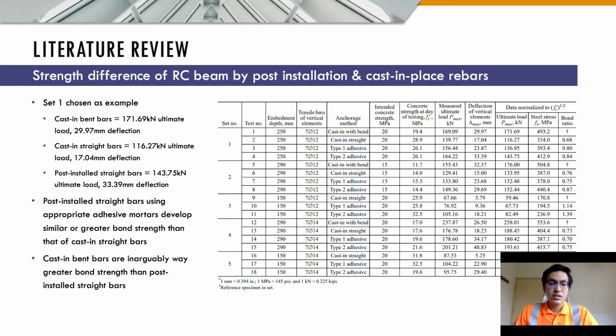With this result, it is concluded that post-install straight bars using appropriate adhesive mortars develop similar or greater bond strength than that of cast-in straight bars. However, cast-in bent bars, which is usually adopted in construction, has greater bond strength than that of post-install straight bars.